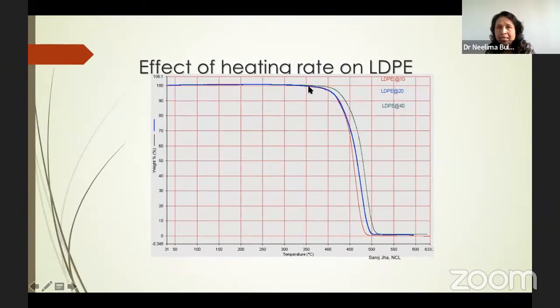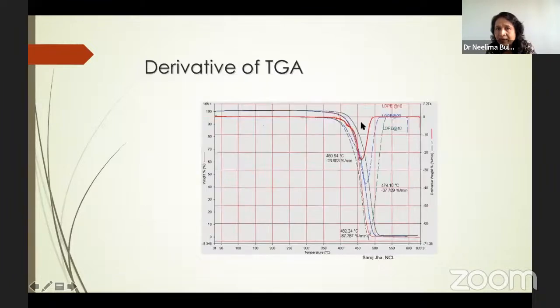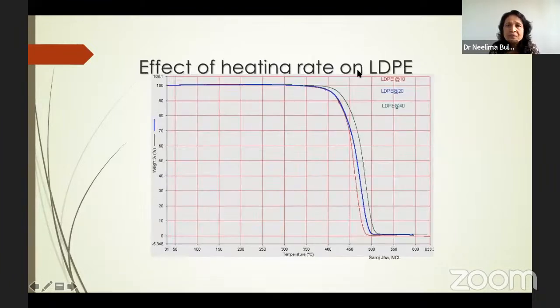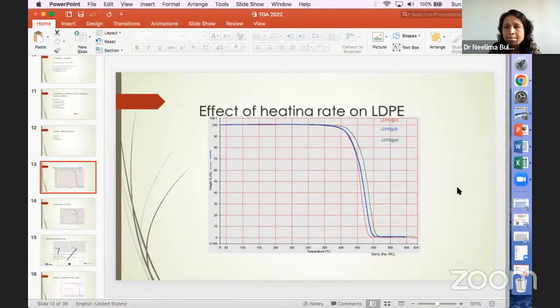The blue curve is at 20 degrees centigrade and the green curve is at 40 degrees centigrade. Now the onset of degradation shifted because of the heating rate, a 20 degrees shift. For the blue curve, the onset is here. And for the green curve, because I have heated it at 40 degrees centigrade, the onset is shifted. Can you see it? Yes, ma'am.